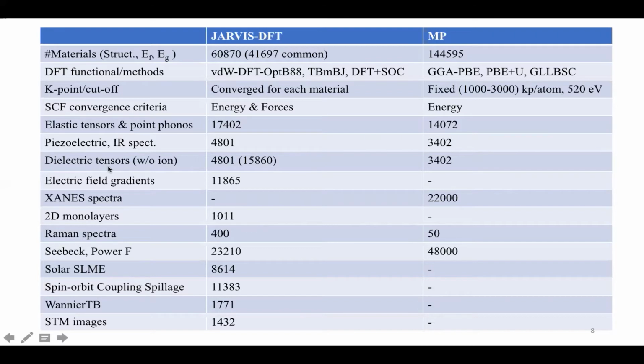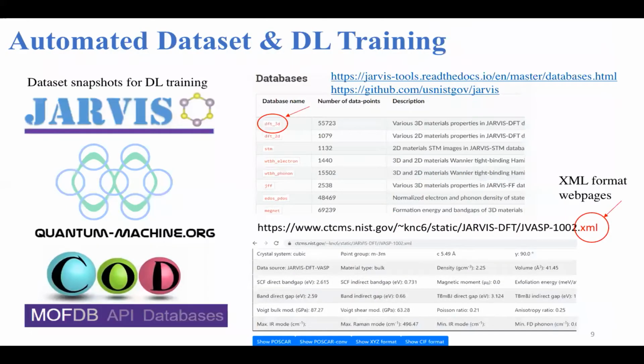We have piezoelectric and infrared spectra and so on. We have dielectric tensors with and without ionic contribution. We have electric field gradient, Raman spectra, solar cell efficiency, and topological spin-orbit coupling spillage for distinguishing topological versus non-topological materials, a Wannier tight-binding database, and an STM image dataset. And there are many others, but for the sake of comparison, I think this would serve the purpose.